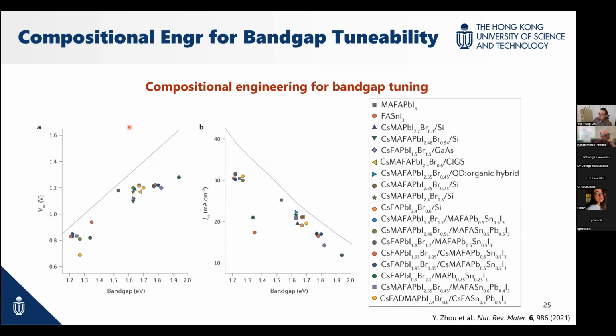Okay, so the next thing I'm going to talk about is regarding the perovskite interface. As we can see, when we change the perovskite compositions, we get a different bandgap material. Especially we focus on bandgaps between 1.6 and 1.8. But we saw a lot of photovoltage penalty a couple of years back. Of course, in these two years, perhaps from last year or the year before, we see a massive improvement in terms of improving these photovoltage penalties.